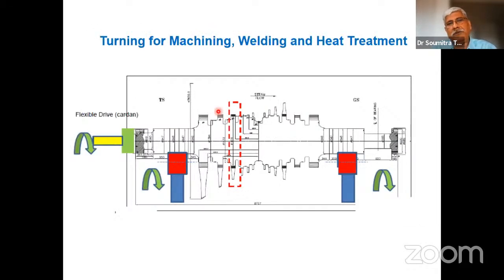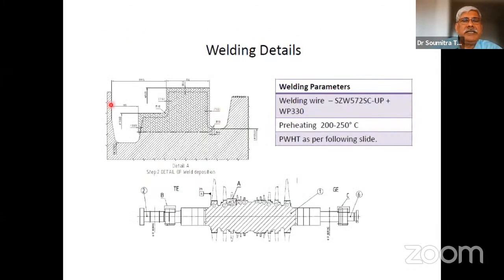So this had to be turned, of course, for machining that part of the disc and then relaying metal over there through welding, submerged arc welding, doing a post-weld heat treatment, making sure that the quality of the weld was appropriate, the material that was weld laid was up to the mark, it had the properties that were required, and there were no defects. So that was our part. So essentially part of the disc had to be machined off and relayed with weld metal, submerged arc welding. This was the welding wire.